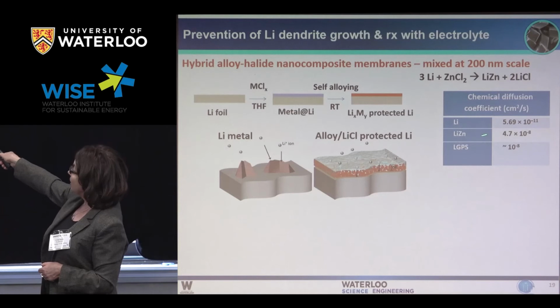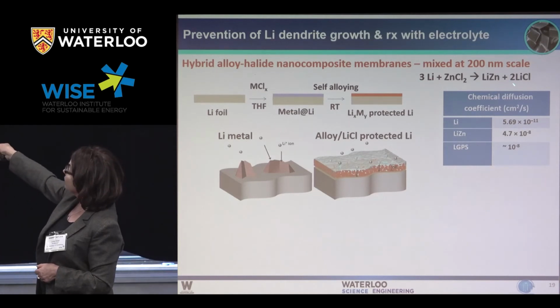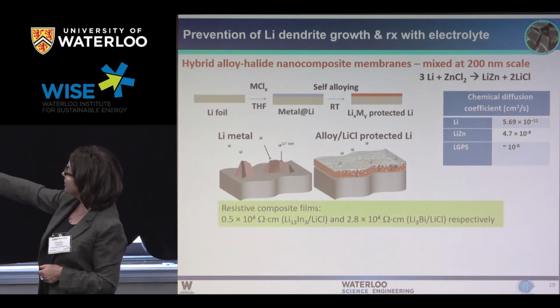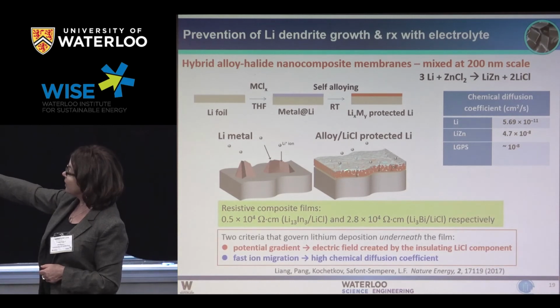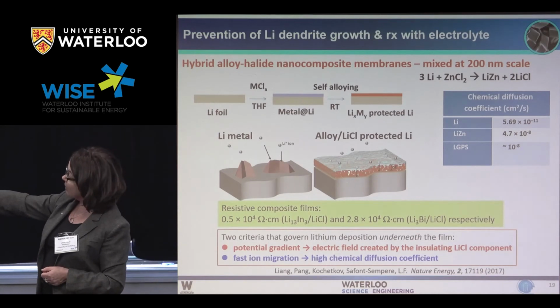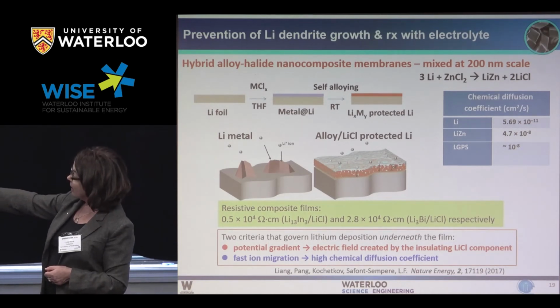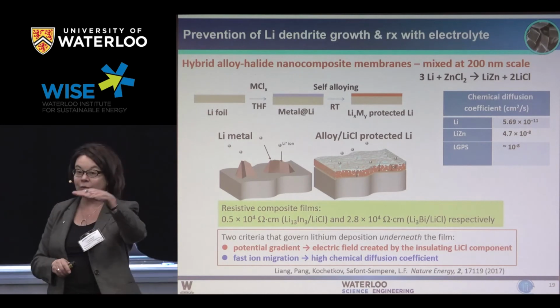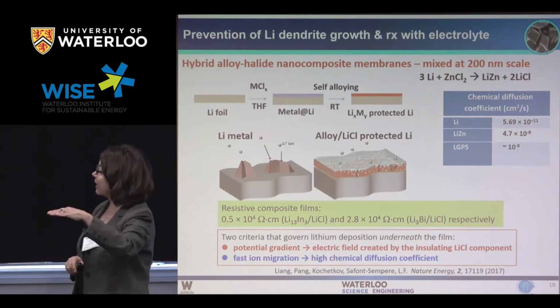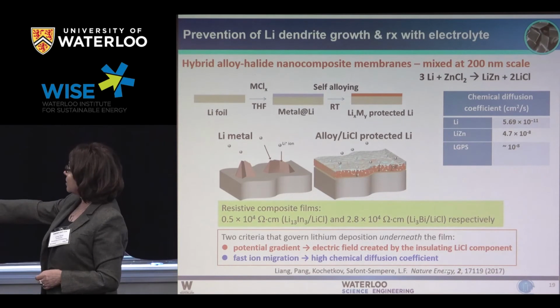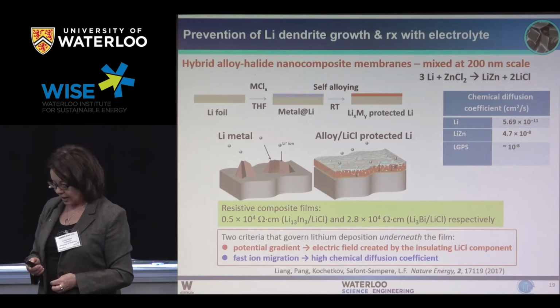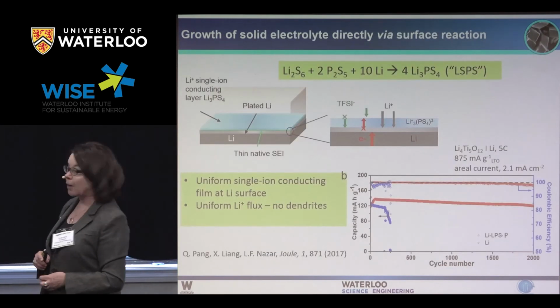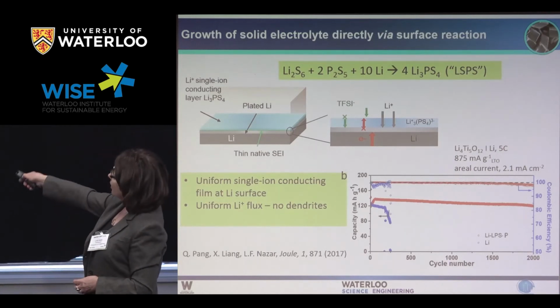But these alloys are metallic. And by virtue of this chemistry, we end up with this complicated interweaving of the alloy and the lithium chloride. And so the alloy allows the diffusion of lithium through the film, and the halide basically makes sure that there is a potential gradient created on that surface that drives the lithium under. So we published this in Nature Energy last year, and it's fast becoming a rather popular topic. And we've also developed other chemical routes to make these phosphosulfide membranes by simple chemistry techniques.